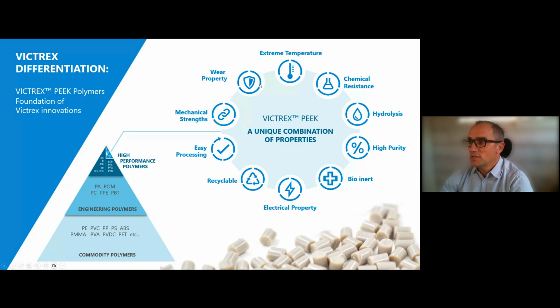So in terms of meeting extreme temperature resistance, chemical resistance, hydrolysis resistance, purity, it's bioinert, with pretty good electrical properties. Obviously, it's a thermoplastic, so it's recyclable. It's easy to process, with pretty strong mechanical strength and wear properties. So what we used to say as a rule of thumb: if you are facing at least 3 of those issues, then PEEK can help, because PEEK ranks, if not number 1, maybe 2 or 3 to address those needs. So, a pretty high-demanding environment. So that's for PEEK.